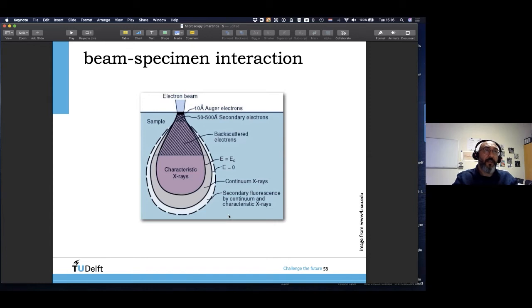It can be starting from maybe half a micrometer, I mean, this distance and this distance, can be somewhere from half a micrometer going all the way up to 5 micrometers, depending on the specimen and depending on your accelerating voltage. Okay, these two things are so important. And again, you can model these with Monte Carlo simulations available on the internet. You can easily find freeware software to model beam specimen interaction.